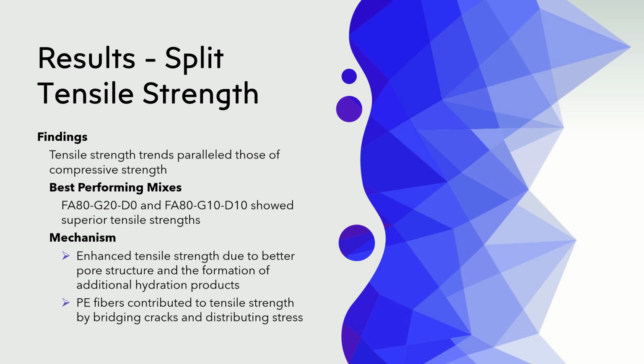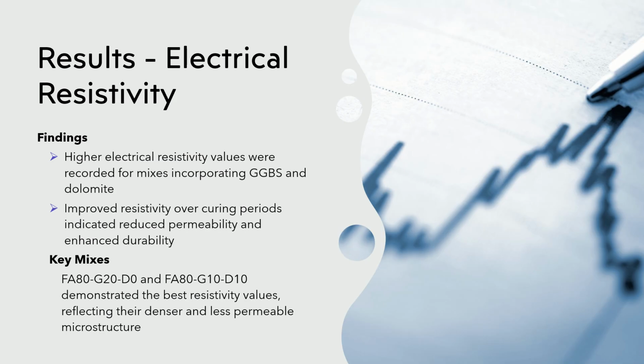Tensile strength test revealed that adding dolomite and GGBS to the geopolymer concrete also improved its ability to resist cracking under tension. Mixes with these materials showed higher tensile strength at 7 days, 28 days, and 90 days compared to mix without them. The electrical resistivity test showed that adding dolomite and GGBS to the geopolymer concrete improved its resistance to flow of electrical current, indicating better durability and lower permeability. Mixes with these materials had higher resistivity at 7 days, 28 days, and 90 days compared to the mix without them. The Fa80G20D0 mix had highest resistivity, suggesting it has fewer pores and is less likely to allow water and harmful chemicals to penetrate.